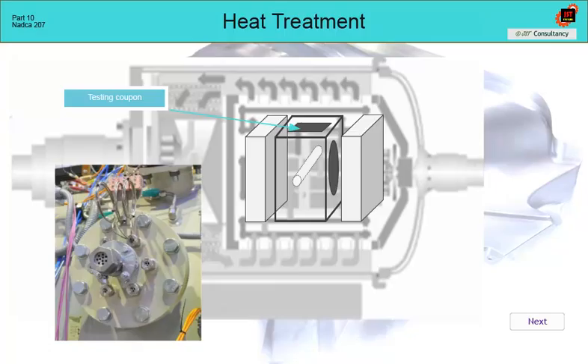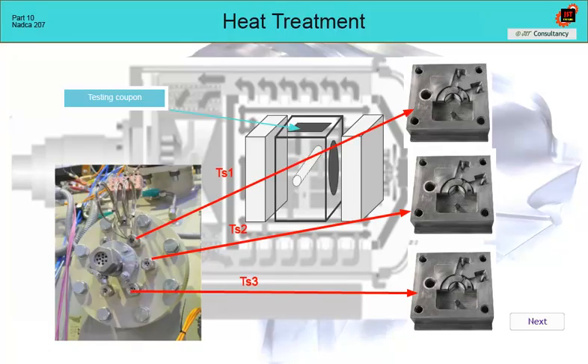There are furnaces where up to 12 batch thermocouples can be used, and therefore a thermocouple can be placed in each insert. We only need to ensure that the individual thermocouples are identified in relation to the hardened inserts. We place TC in the largest of them and at the same time select the TS thermocouple in the furnace program, stored in the same insert as TC, intended for process control and delta T evaluation.